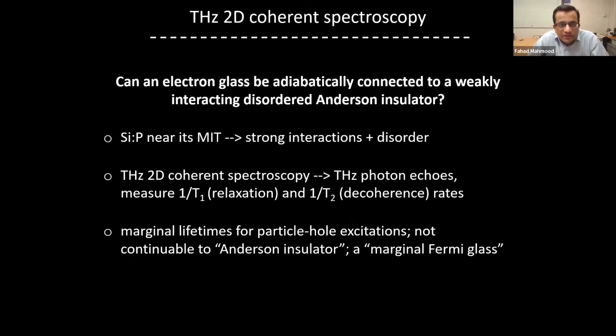So even on the insulating side, where you still have strong interactions present and you have disorder, it's a strongly correlated system, as I'll show shortly. And we attacked this with this new technique of terahertz 2D coherent spectroscopy. What we observed were these things called terahertz photon echoes. From there, we can extract both the energy relaxation and decoherence rates for whatever emergent particles there may be. And from there, we see how they behave with frequency and temperature.